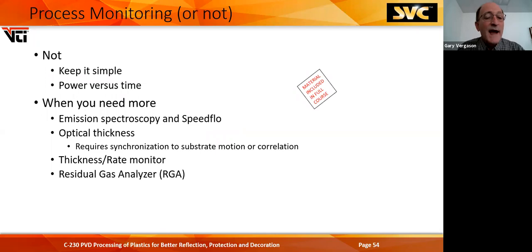Process monitoring or not. You want to keep it simple. Some people use a power versus time kind of process setup. But when you need more, there's emission spectroscopy and Speedflo, optical thickness measuring, rate monitors, residual gas analyzers for looking at what's in there. The simpler you can make the monitoring, the longer your process integrity will hold up.